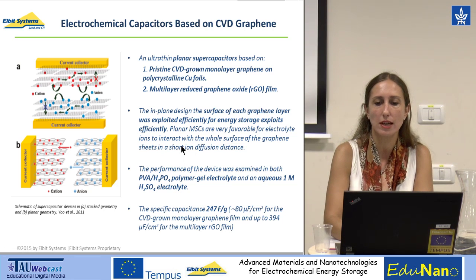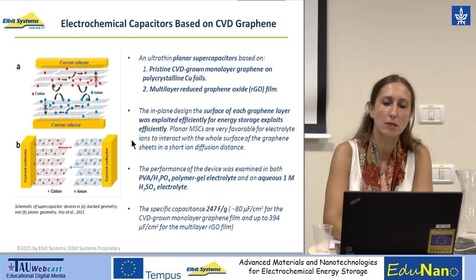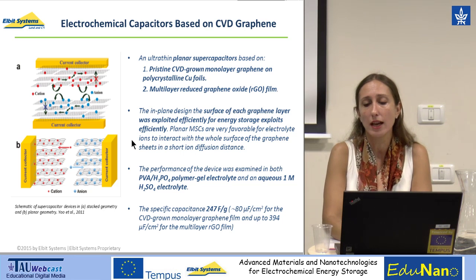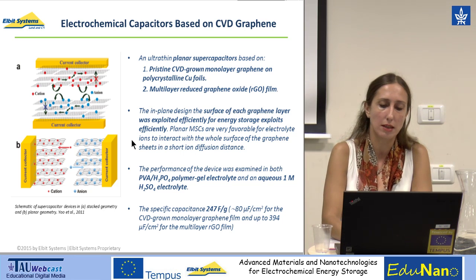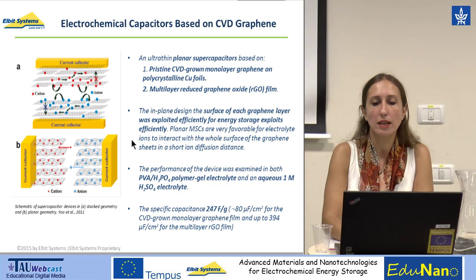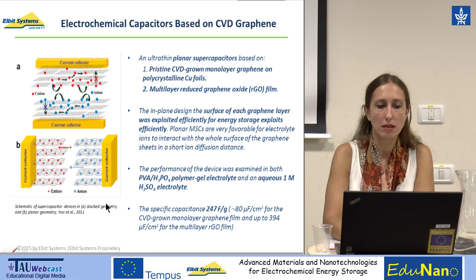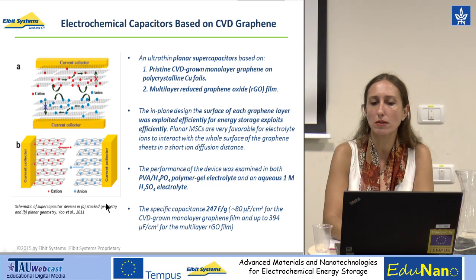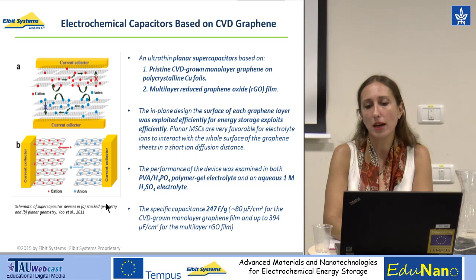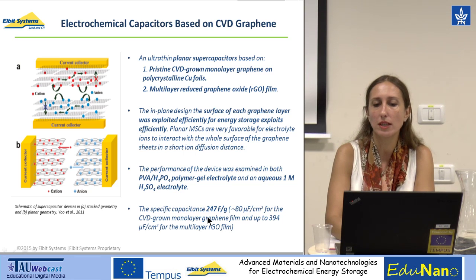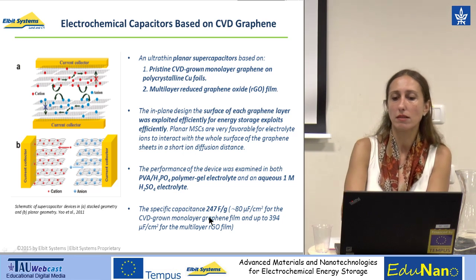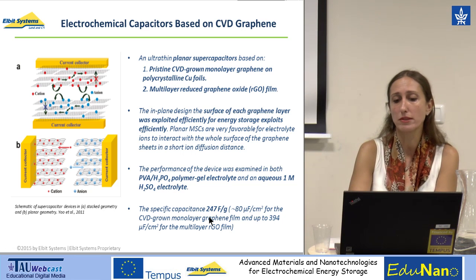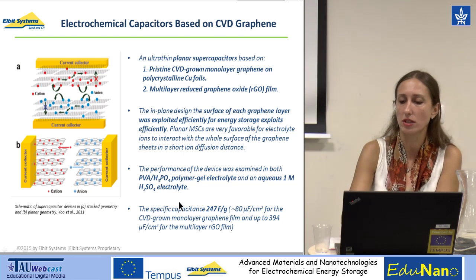So the performance of this kind of device was examined in both PVA phosphoric polymer gel electrolyte, as well as in an aqueous 1 molar sulfuric acid electrolyte. And what they attained are specific capacitance values of 247 farad per gram, approximately 80 microfarad per square centimeter for the CVD grown monolayer graphene film, and up to 394 microfarad per square centimeter for the multi-layer RGO film.